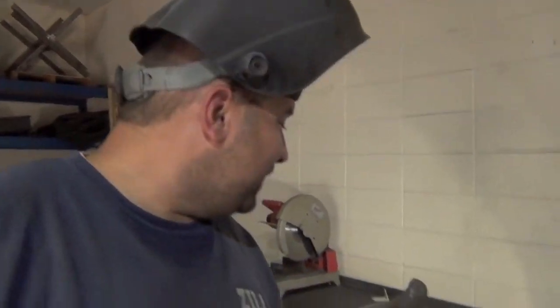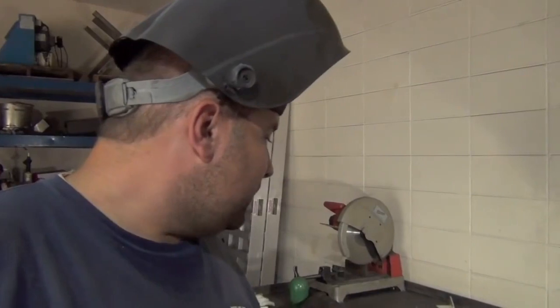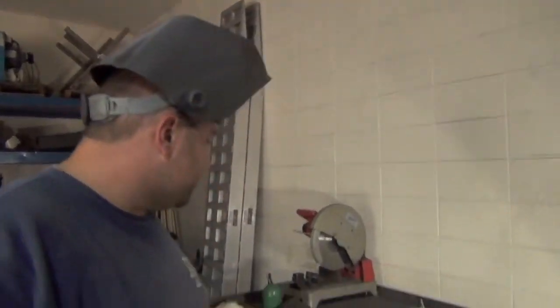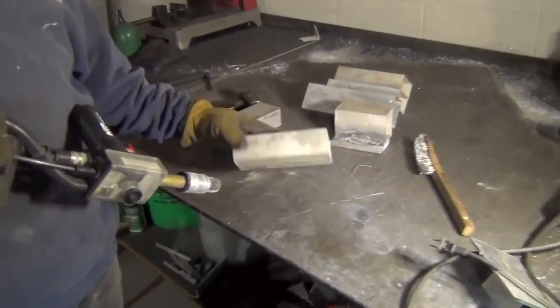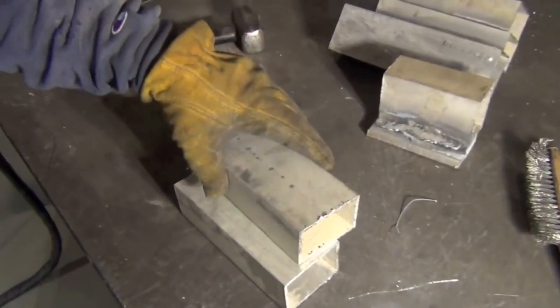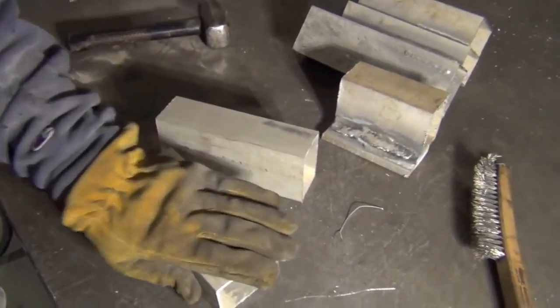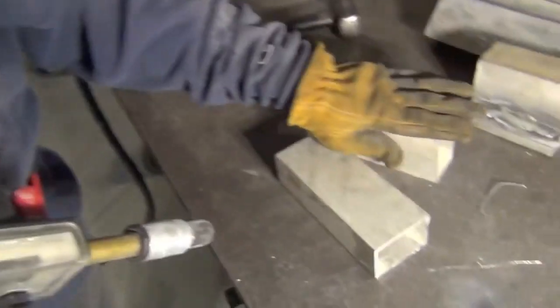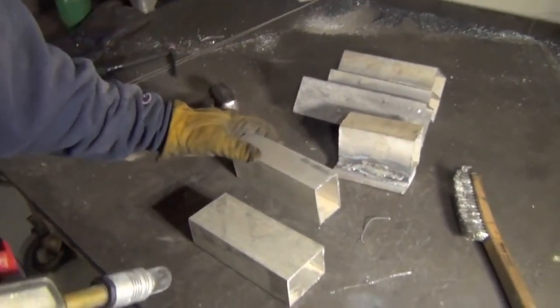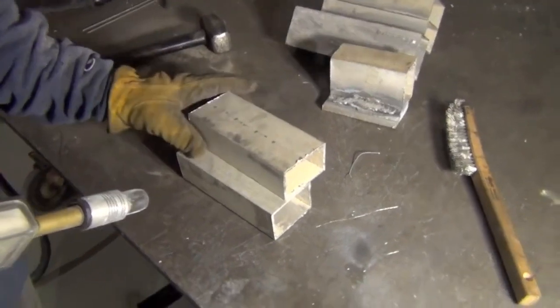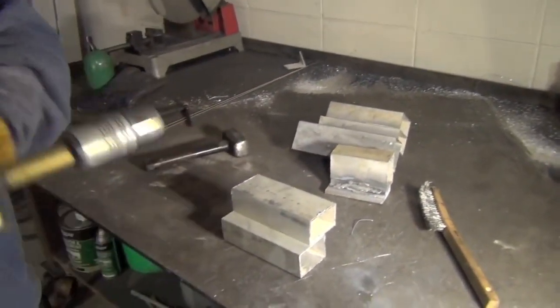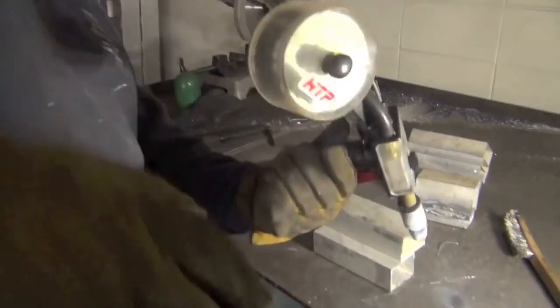Alright, Peter? So Steve, since we tried cleaning this aluminum, Chucky tried to clean it, I tried to clean it, and we both were only semi-successful. We still see contamination with the TIG machine. So what I will do is, this aluminum that has been laying outside my shop for 2 years, we will tack together, and I wipe it off with a glove, Steve. We're not gonna use a wire brush on this. We'll see how good your wire really is. Let's tack it up.